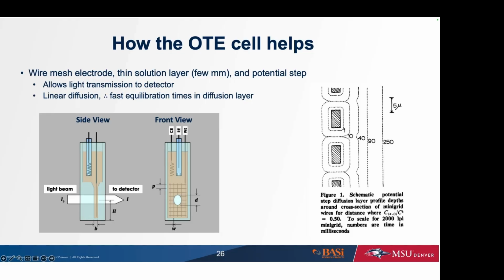So the requirements are, we want the wire mesh electrode to allow light to pass. We want it to enable facile diffusion to the electrode so mass transport can be neglected, and our equilibrium can be established quickly and then pushed towards either the oxidized or the reduced species by the potential. We want a thin solution layer. We want the cell thickness to be thinner than the diffusion layer so that the mass transport can be neglected. Again, we're trying to get the diffusion of the species to the electrode surface as fast as possible so we can build up the concentration of the oxidized or reduced species and then see the spectral signal of those species grow in over time.